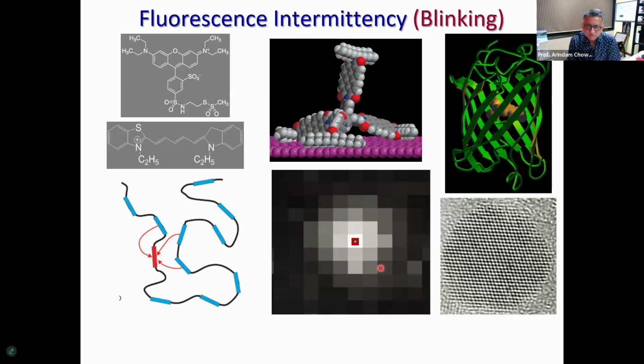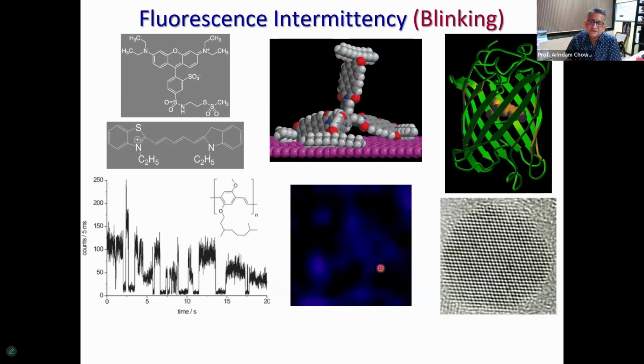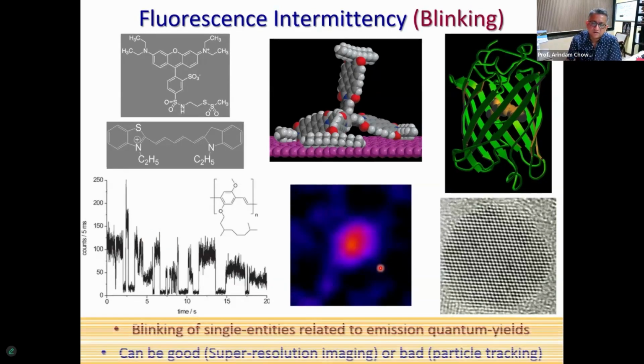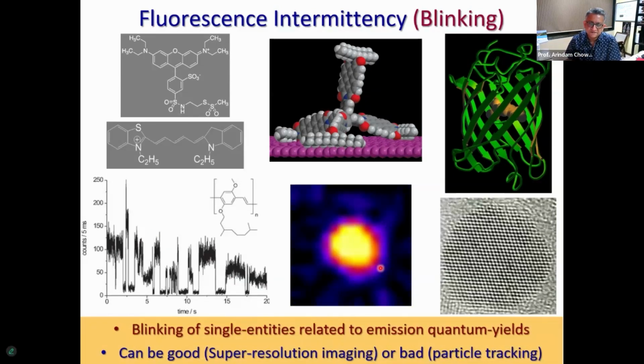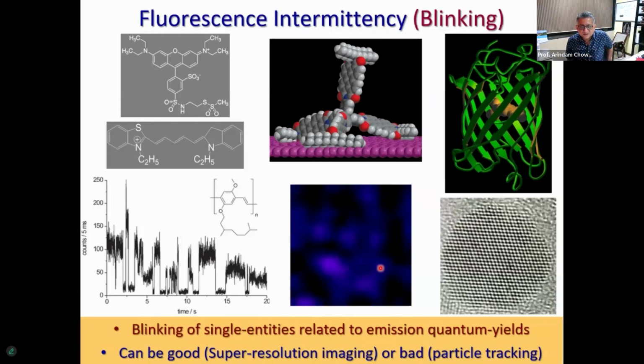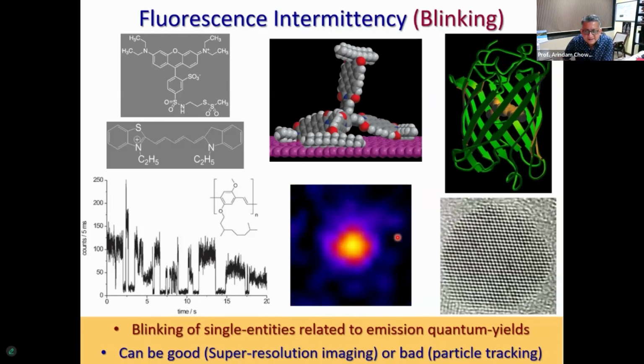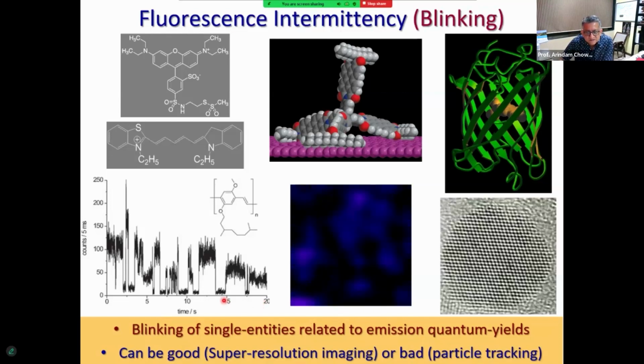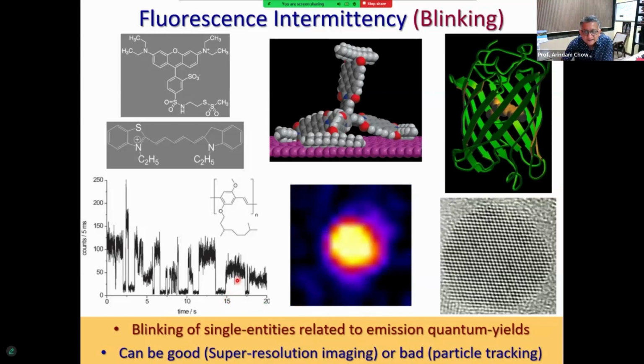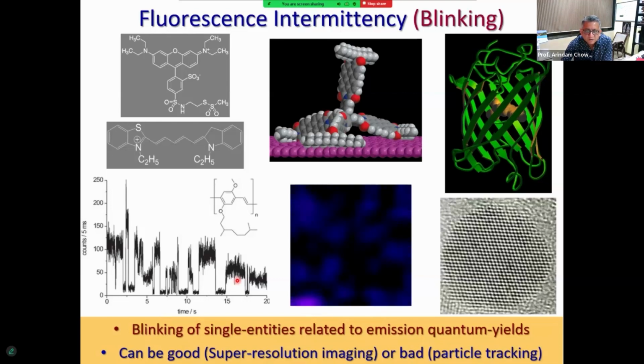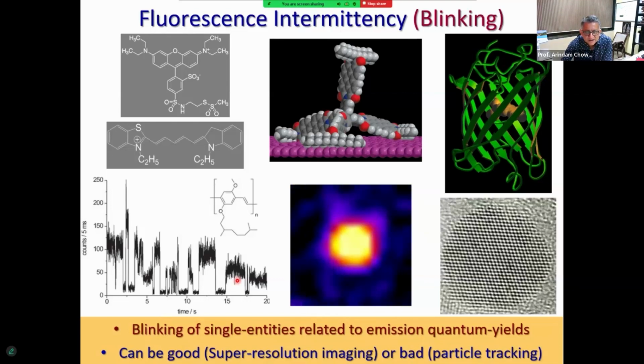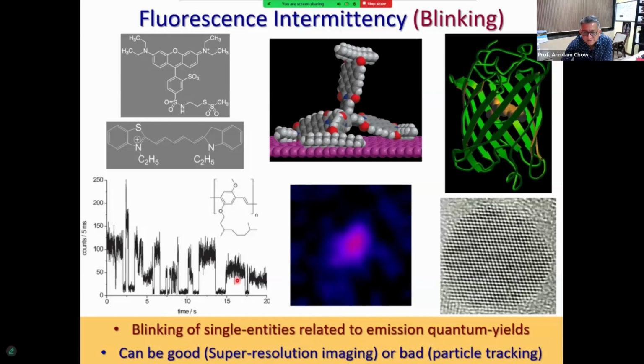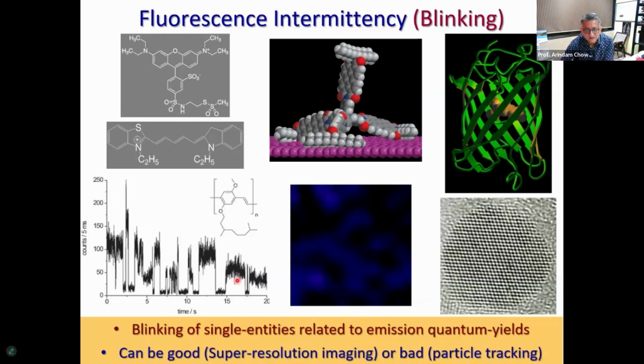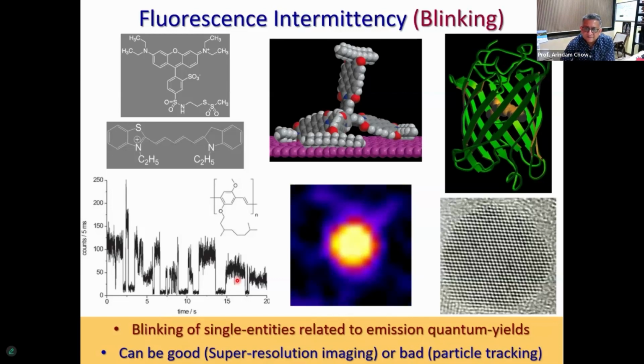But if I collect a movie of the spot, you see something like this, where light's coming out and then it stops coming out. And this is the phenomena called fluorescence intermittency or blinking. And this is very, very characteristic of single molecules and single nanoparticles. And this phenomena is a temporally random process, and it can be good for certain aspects, such as super resolution imaging, which utilizes the idea of blinking of molecules, but it can also be bad for certain other aspects, which is, for instance, particle tracking.